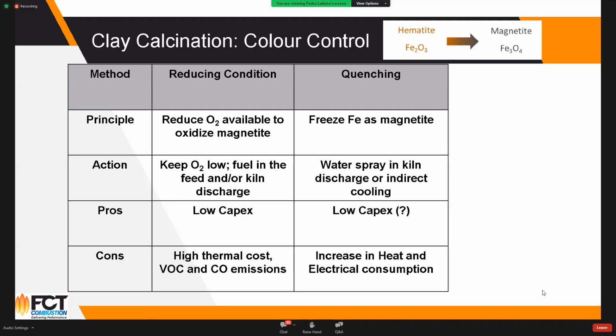When you come down with the temperature, it becomes hematite again, and we try to freeze it as magnetite just by quenching. You might use water spray in the kiln discharge, or you can use indirect cooling. That might be, depending on the configuration, low capex. I leave a question mark here because normally indirect cooling is not the cheapest option. But either way, you will increase heat consumption and electrical consumption by applying this methodology.